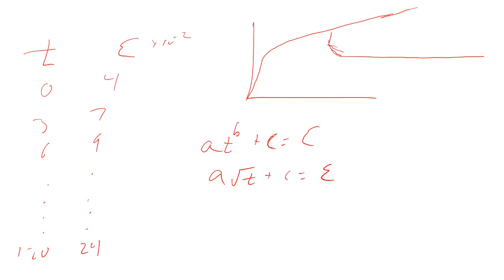And it turns out that 2 square root of T plus 4 is what I got when I checked it in MATLAB for an R squared value. I went through and actually digitized this plot and then fit the data, and if you just plug this in, this gives you an R squared value of like 0.98.